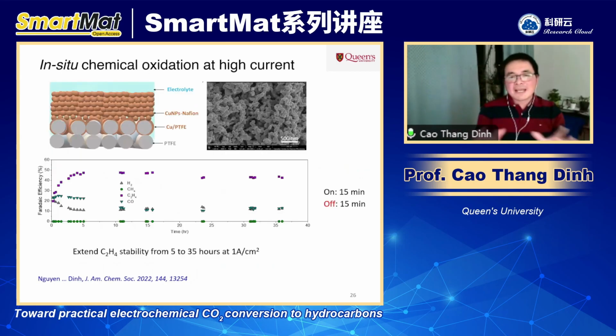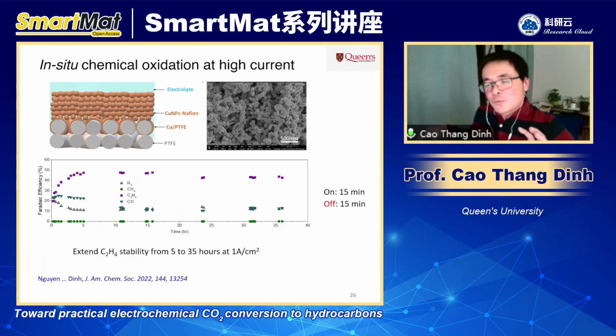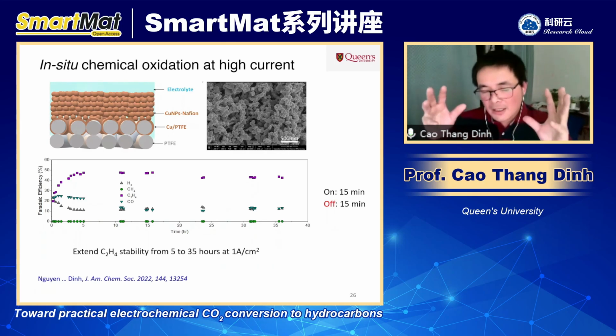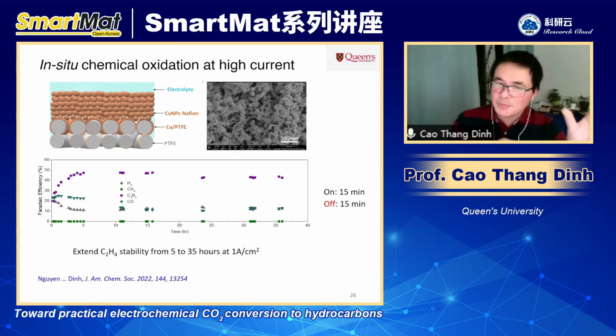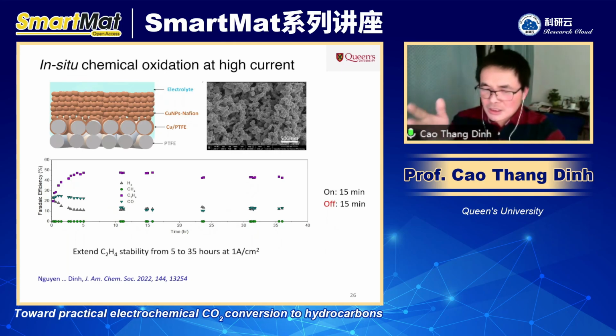And we also use exactly the same strategy, but we want to run the reaction at much higher current. So this is a 1 ampere current, and the previous one is 150 milliamperes. And in order to run a high current, we need to make a 3D catalyst. We need a lot of active sites. So we spray the copper nanoparticles on the PTFE, and then we run the reaction at 1 ampere. And then we can extend the lifetime from about 5 hours up to 30 to 35 hours, having pretty good selectivity, like 40 to 50% of ethylene. So